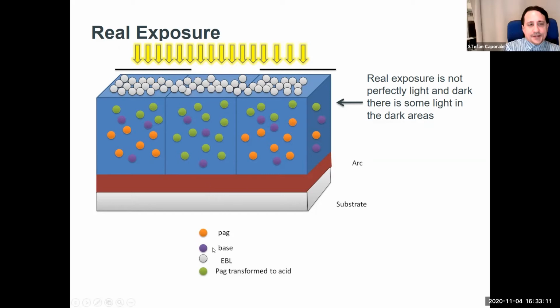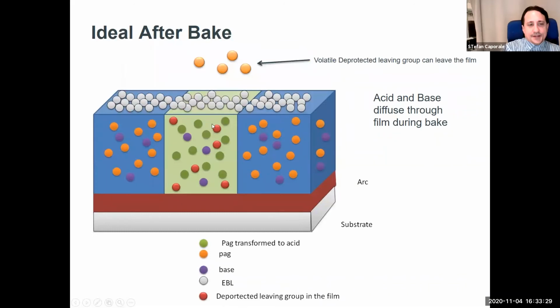And that's one of the big reasons we put the base in these materials, is that we're buffering that top loss there, so we don't lose that film and have that acid migrate down, and you have a greater acid concentration in the exposed regions, and it's enough to overcome that buffering of the base. After your bake, your polymer in the acid region would deprotect. You can get outgassing of your leaving group, and again, depending on the fab and where it's being worked, that can be good and bad. And you don't want any of that to occur during the exposure, it's fine if it happens normally during the bake. So again, you need to make sure your chemistry is only happening after exposure on the hot bake. And again, controlling the amount that's outgassed is also something for environmental concerns.